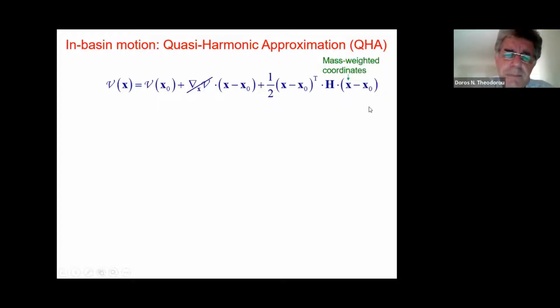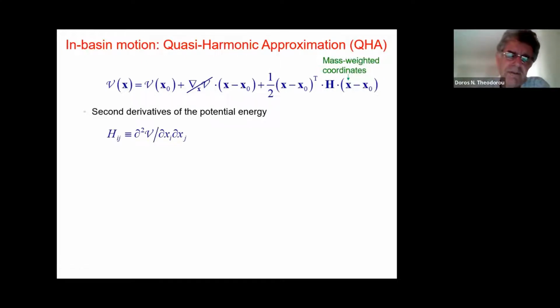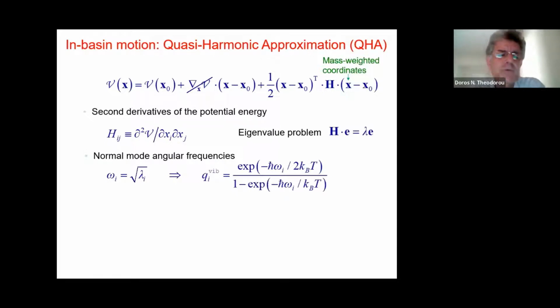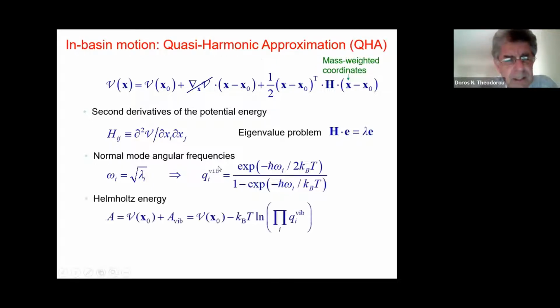But this is a very important term, the second order term. This H is the Hessian matrix of second derivatives of the energy with respect to the atomic coordinates. And by diagonalizing this Hessian, we can obtain normal modes for the vibrational motion of the glass while it is configurationally arrested in the vicinity of this minimum. Each such normal mode of vibration is associated with a vibrational partition function. So we can define a vibrational free energy, which is added to the energy of the minimum, or the inherent structure energy, and gives us a Helmholtz energy for the glass as long as it is trapped in the basin.